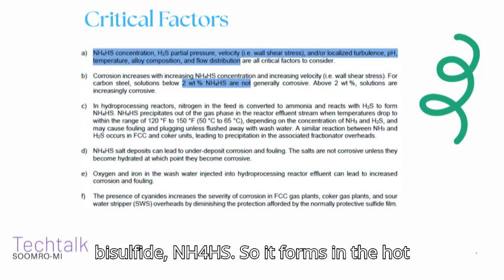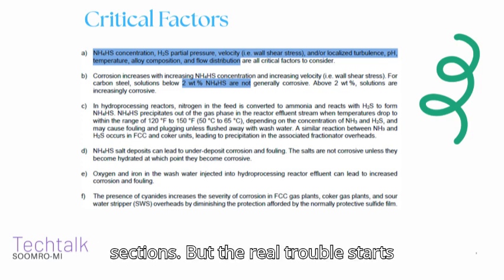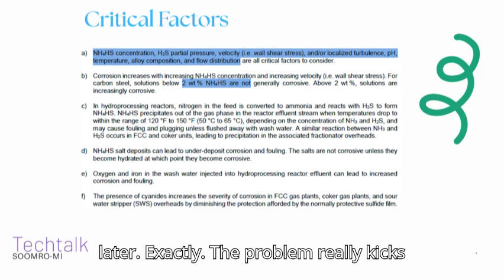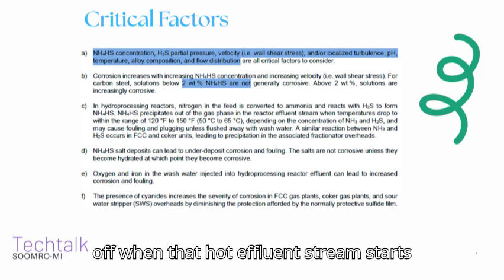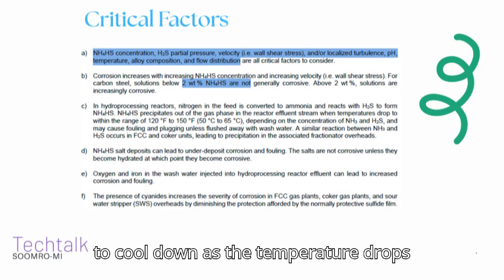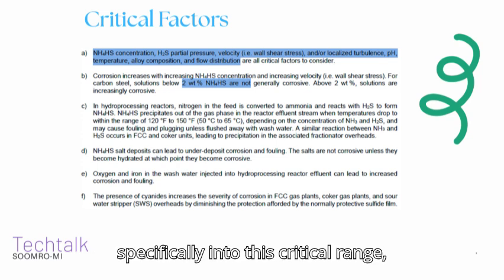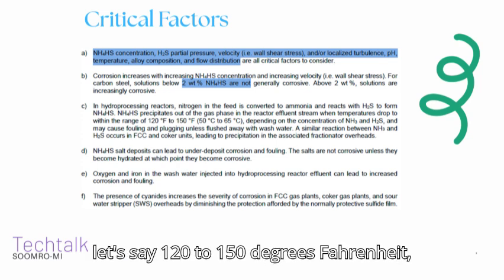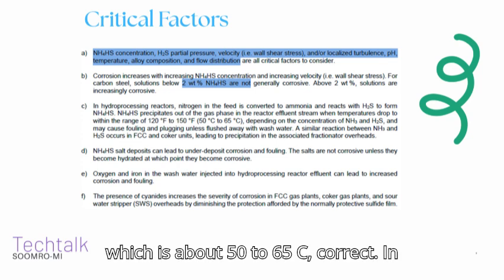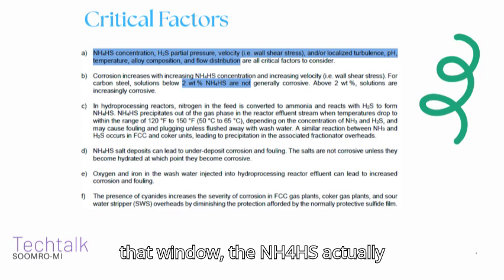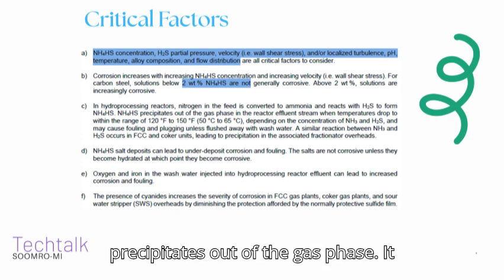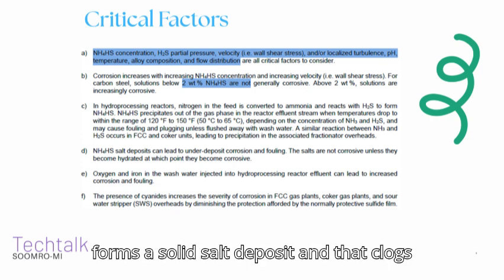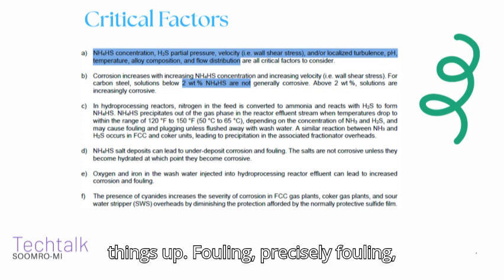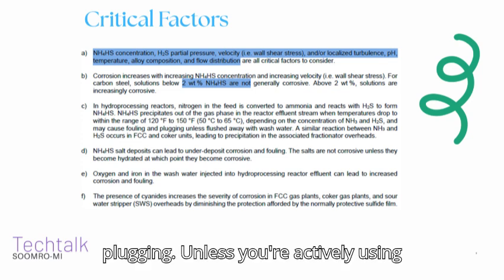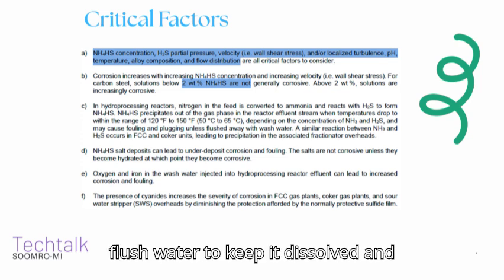So it forms in the hot sections, but the real trouble starts later. Exactly. The problem really kicks off when that hot effluent stream starts to cool down. As the temperature drops specifically into this critical range, let's say 120 to 150 degrees Fahrenheit. Which is about 50 to 65 C. Correct. In that window, the NH4HS actually precipitates out of the gas phase. It forms a solid salt deposit. And that clogs things up. Fouling. Precisely. Fouling, plugging, unless you're actively using flush water to keep it dissolved and moving.